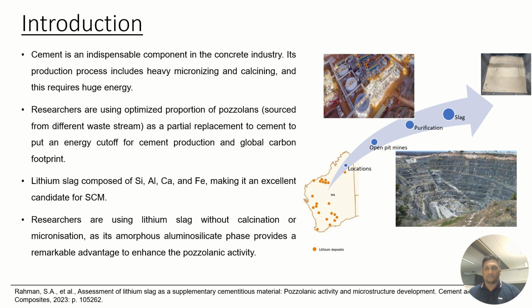Lithium slag is composed of silicon, aluminum, calcium and iron, making it an excellent candidate for supplementary cementitious material. Researchers are using lithium slag without calcination and micronization, as its amorphous aluminosilicate phase provides a remarkable advantage to enhance the pozzolanic activity. In Western Australia, a discrete number of lithium mining sites have an open pit extraction system, and after lithium purification, lithium slag is generated, and this is currently disposed of as backfill.